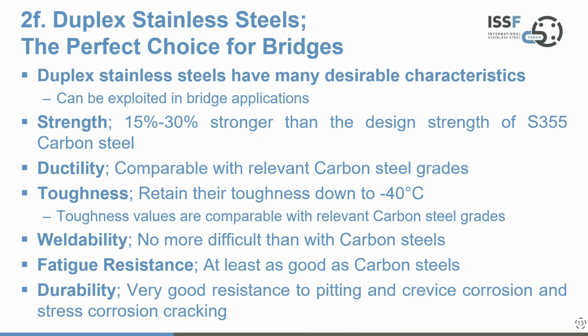So I'd like to say a little bit about duplex steels. Why are these a good choice? Why are they indeed the perfect choice for bridges? As I've said a moment ago, they have many desirable characteristics. First and foremost, the strength of these steels is generally 15 to 30% stronger than the design strength of a standard carbon steel. Their ductility is comparable with relevant carbon steel grades, and they retain their toughness down to -40 degrees centigrade. Toughness values equally are comparable with carbon steel grades.